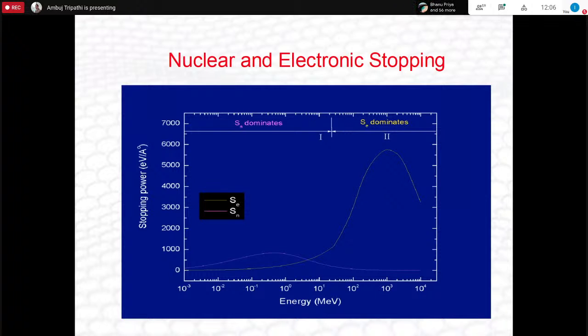Of course, this plot which we always show is the stopping power. This is for one particular ion beam and a particular target. So with these combinations it will keep on changing, and the actual values will change for all the different systems. But overall, you can say that somewhere in the order of a few hundreds of MeV, this peak will come, which we refer to as the Bragg peak, and then this will also start going down. So these are our main areas where we work.